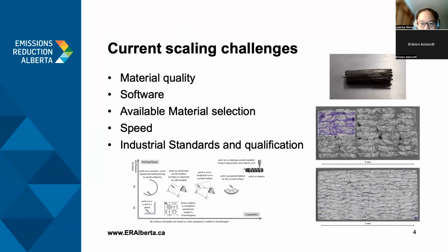Now, the image you see below also shows all the purple parts, but you can see that there's a huge reduction in the total void content. I think we're able to reduce this to about 4% using a patented in situ consolidation process.